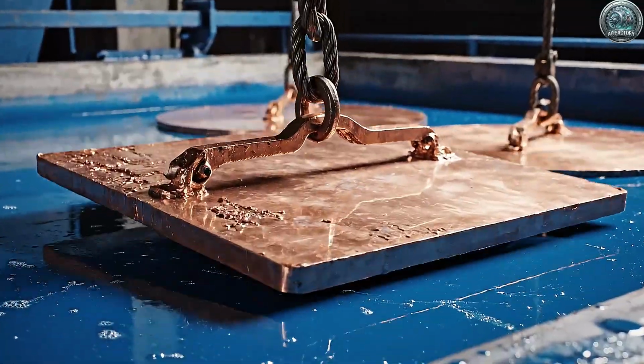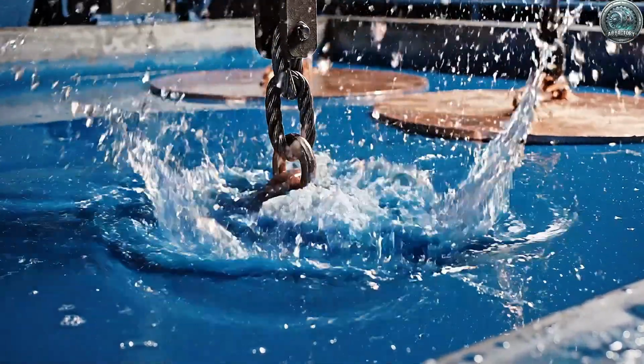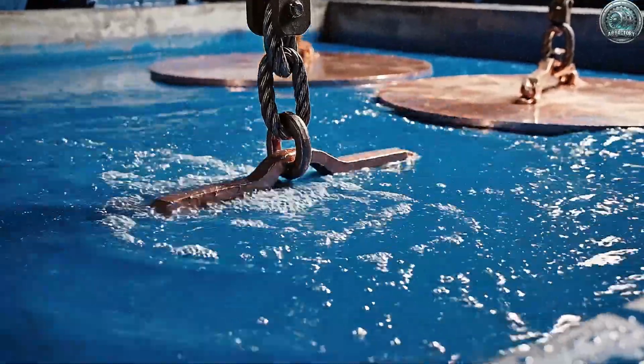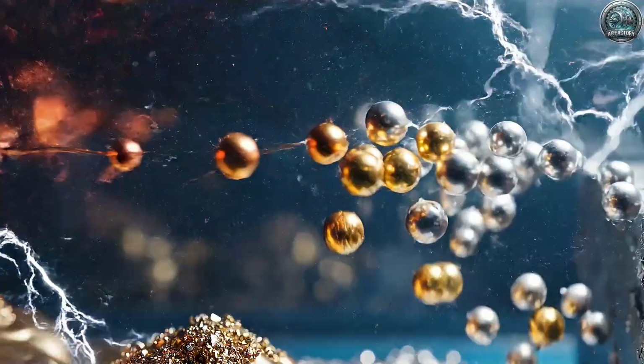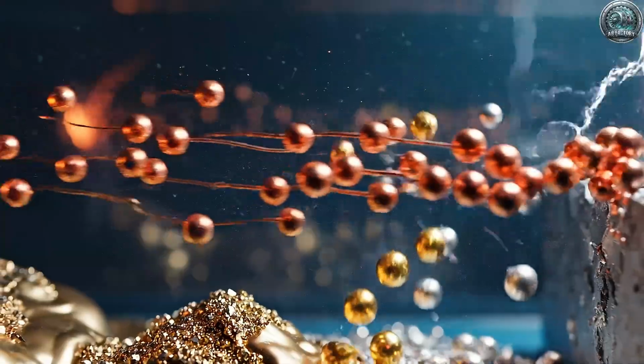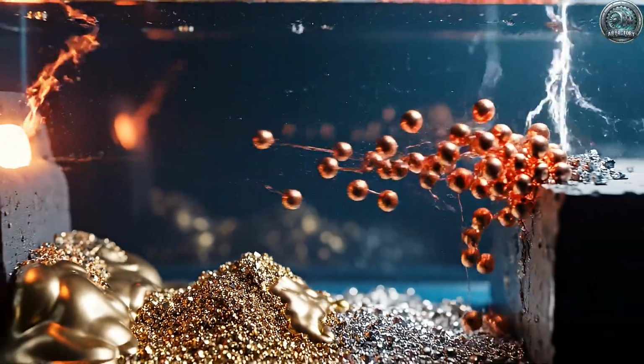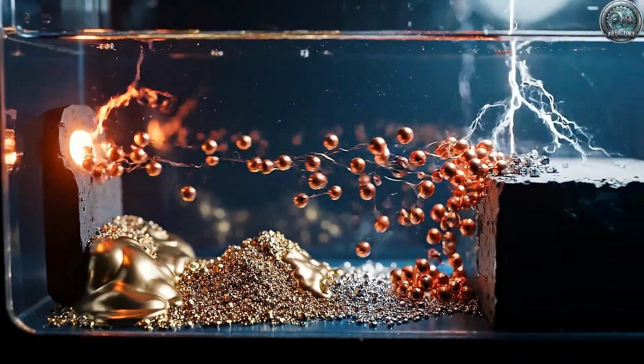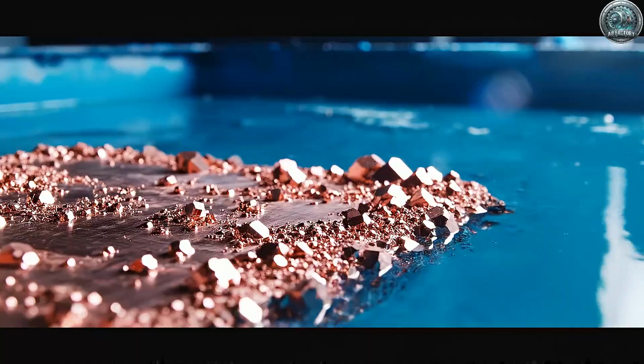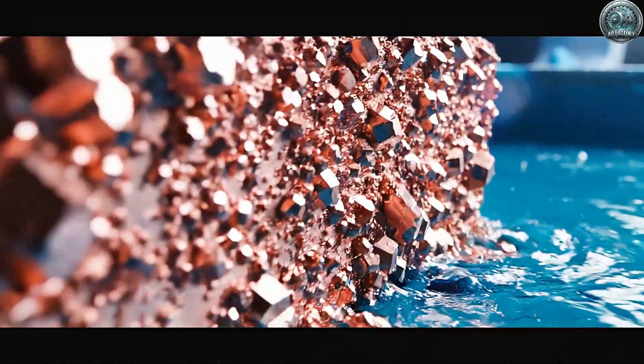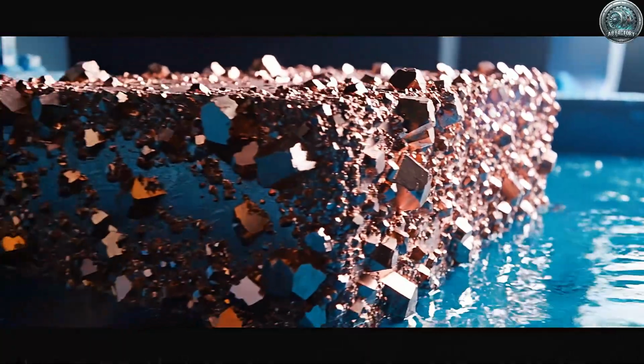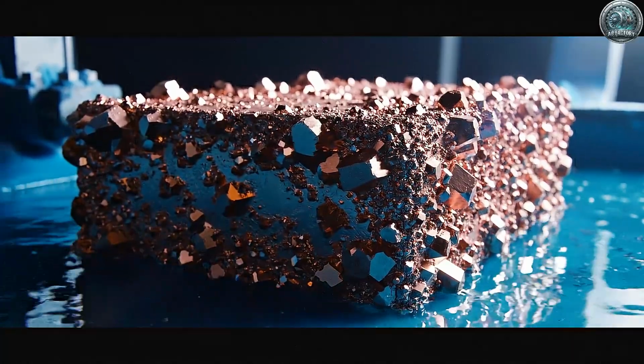Submerged in an acid bath, the anode plate begins its slow dissolution, driven by a constant electrical current. Copper atoms travel to the cathode, but gold is too heavy. It falls to the bottom, collecting as sediment. Pure copper builds up on the cathode plate, growing crystal by crystal into a thick, marketable slab.